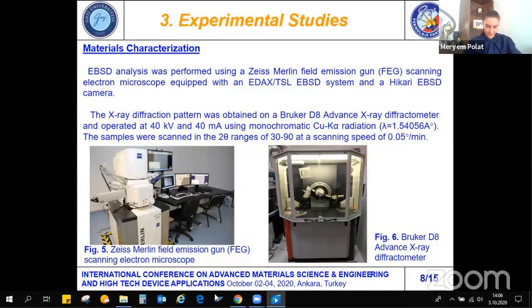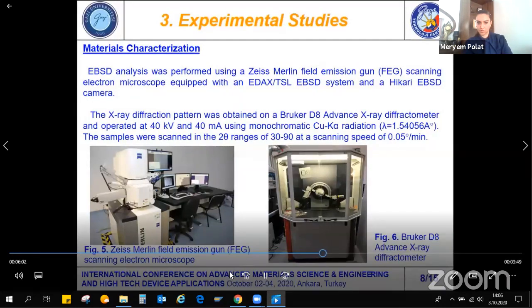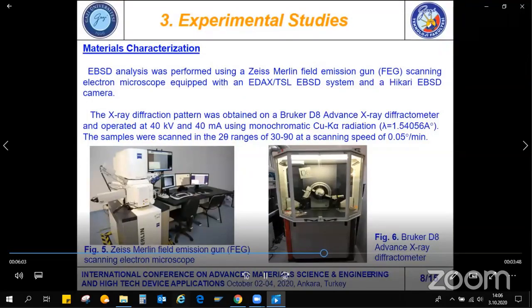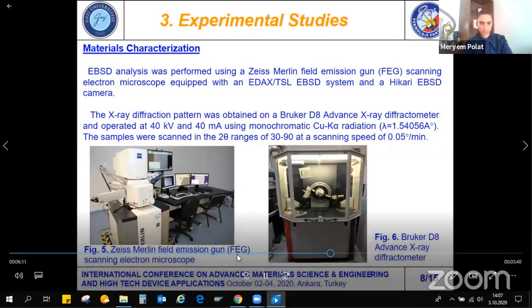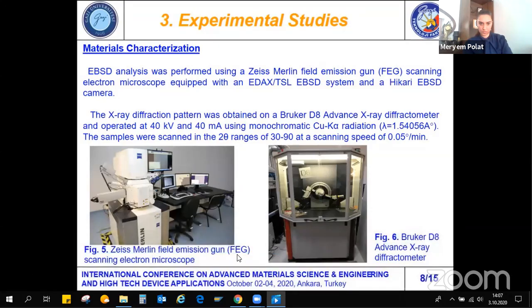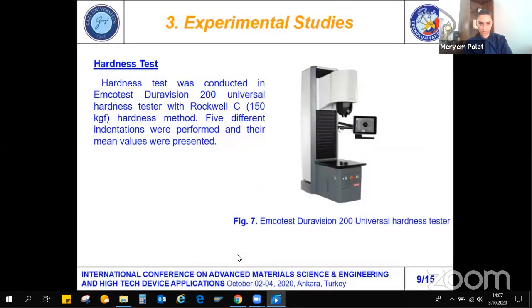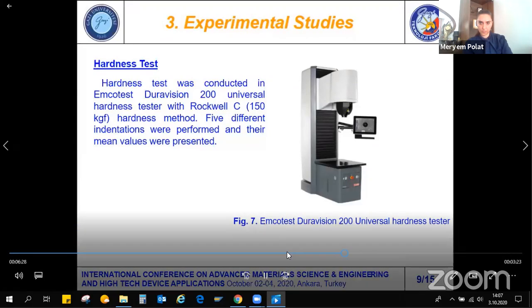The X-ray diffraction pattern was obtained on a Bruker D8 Advance X-ray diffractometer, operated at 40 kilovolt and 40 milliampere using monochromatic copper K-alpha radiation. The samples were scanned in the 2 theta range of 30 to 90 degrees at a scanning speed of 0.05 degrees per minute. Also, a hardness test was conducted in an EMCO-Test DuraVision 200 universal hardness tester with the Rockwell C hardness method. 5 different indentations were performed and their mean values were presented.